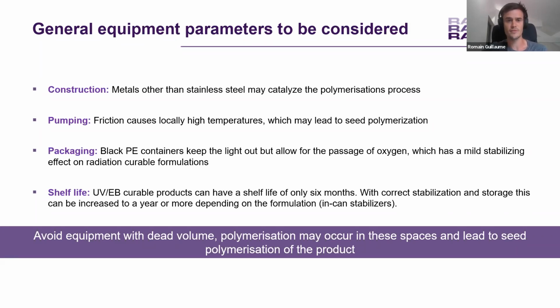About the shelf life, UV or EB (electron beam) curable products can have a shelf life of only 6 months, and with correct stabilization and storage, this can be increased to about a year or more, depending on the formulation itself. Also, something very important is to avoid equipment with dead volume. Polymerization may occur in these spaces and also lead to seed polymerization of the product itself.